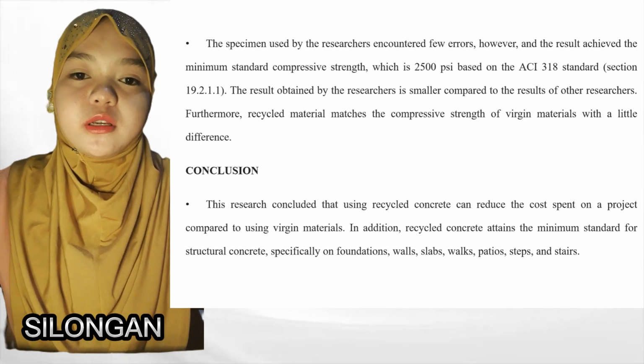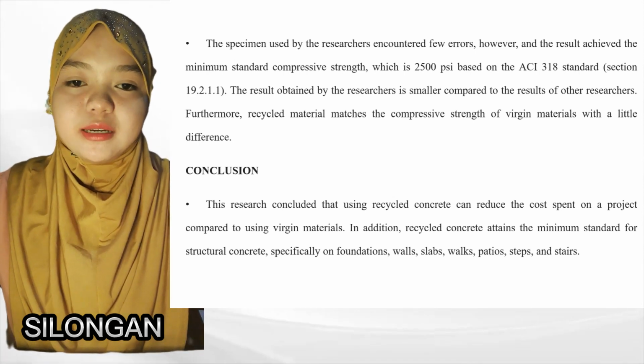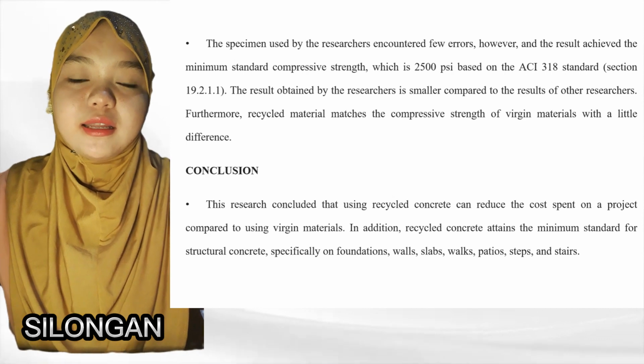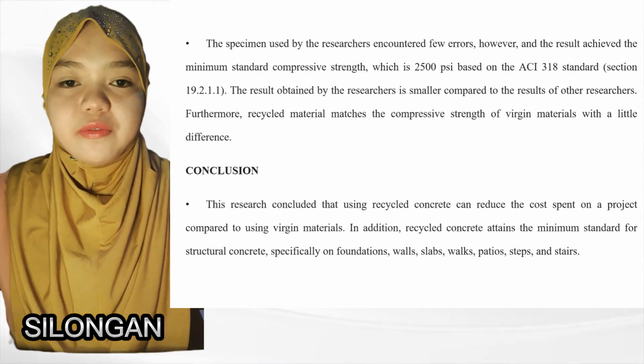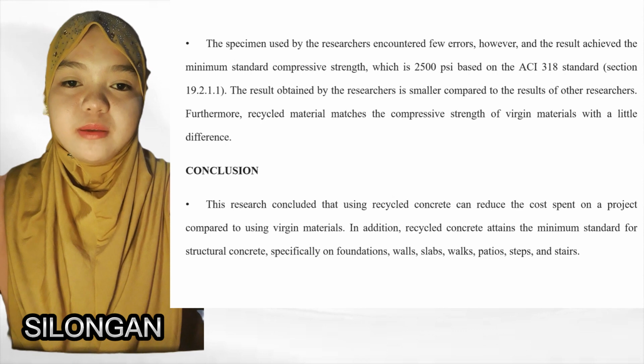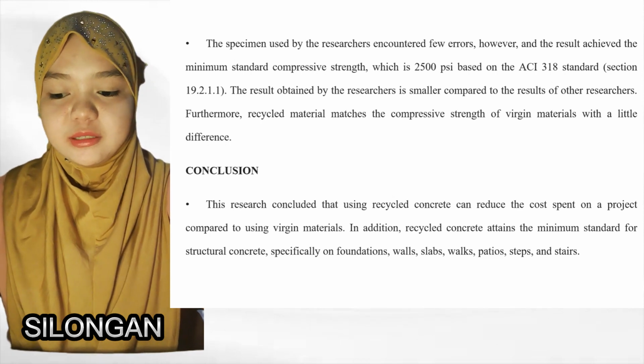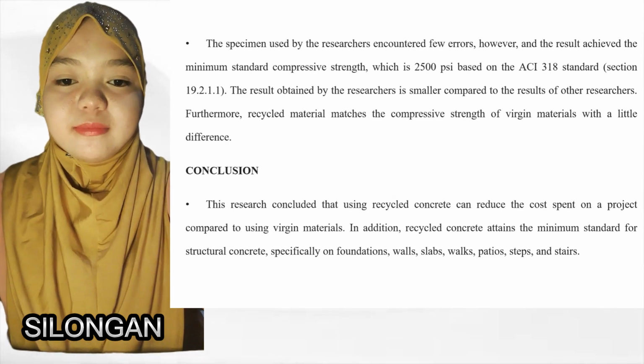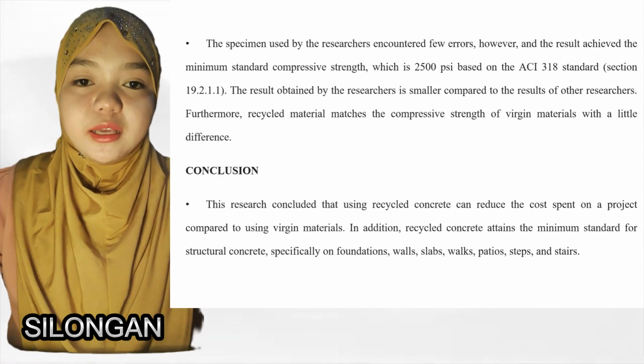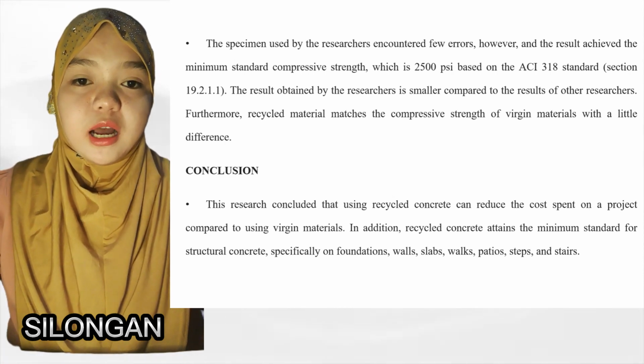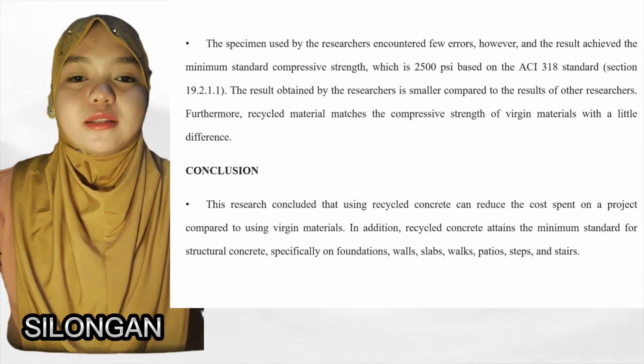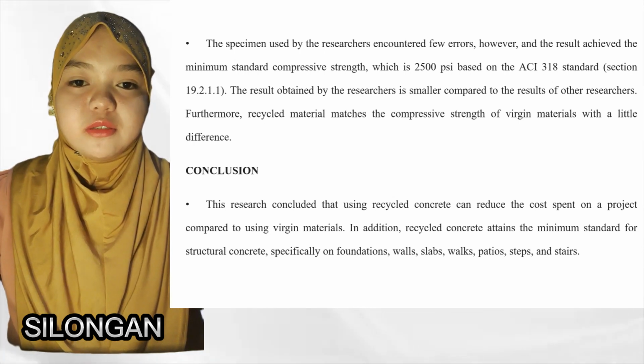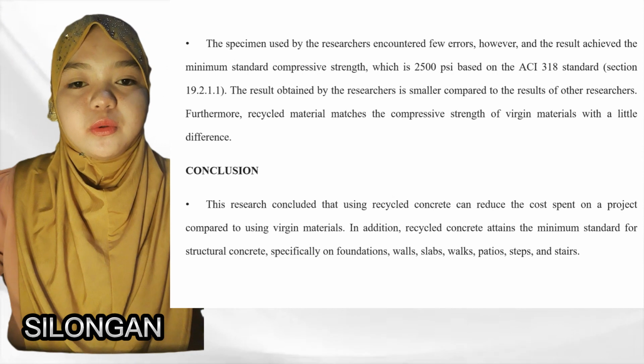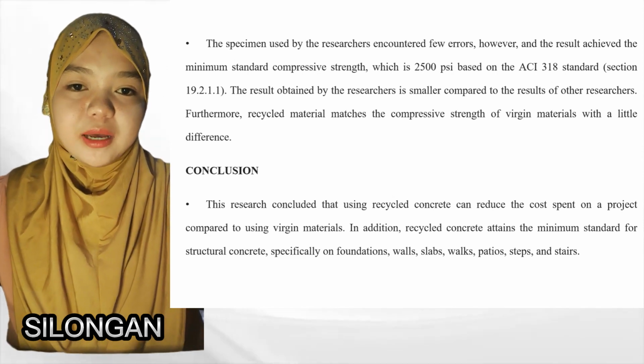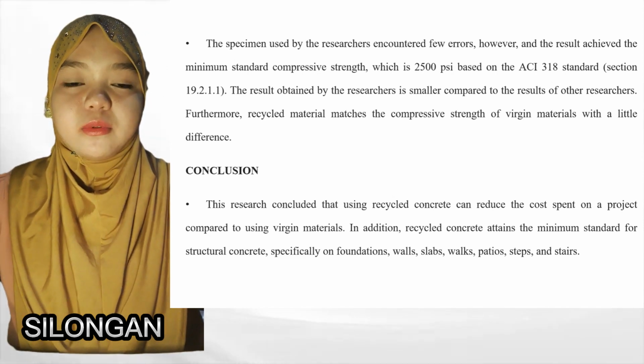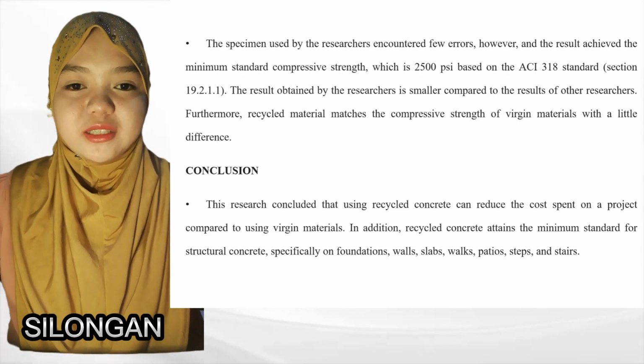Comparing the compressive strength of virgin material and recycled material, recycled material can attain the standard strength for compressive strength. However, virgin material is stronger than the recycled material, with just a little difference. Researchers encountered many errors in creating the product, but still managed to attain the standard strength for compressive strength. With that, the researchers concluded recycled material can match the virgin material in terms of its compressive strength.